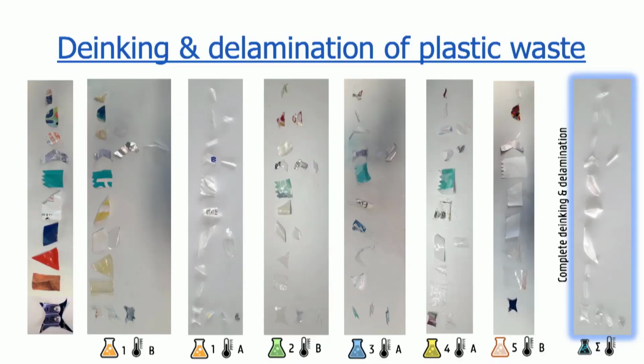Now I will shortly introduce our research into the de-inking and delamination of plastic waste. What we have done here is we tested different mediums and different conditions, and we optimized our procedure until at the end we had a method that was able to remove all the inks and the adhesives present on plastic films. You can see here some results we obtained, with, on your right-hand side, a completely de-inked plastic film stream.